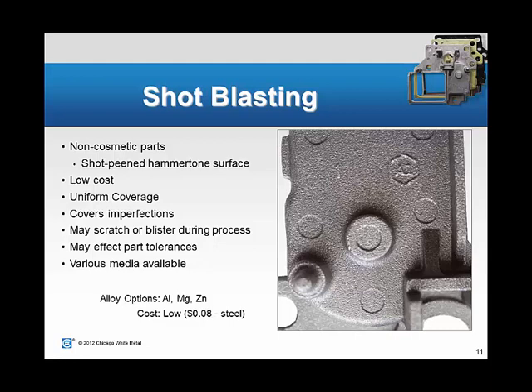The steel shot is, like I said, relatively aggressive to the part, so for any really tight tolerance features, you may have some issues keeping that tolerance after the process. And there are various media available. Again, the example that we show here was processed with the steel shot for the aluminum part, but there are different media options available that will allow us to process magnesium or zinc as well. The cost for this process, for this part at a 500-piece batch size, was 8 cents. That's with the steel media. So that's the baseline that we start with.